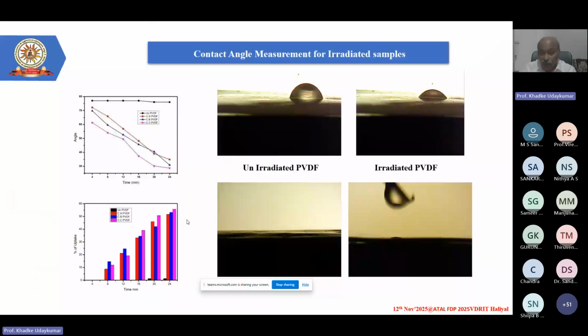Well, another important thing, I don't know whether it will work or not. See, a porosity is created. What is another conventional method to understand that porosity is there? Now when you have an unirradiated film, you can see that the water drop is sitting on the surface. When you have an irradiated one, the water drop is going inside. This is possible only when the irradiation beam has created porosity.